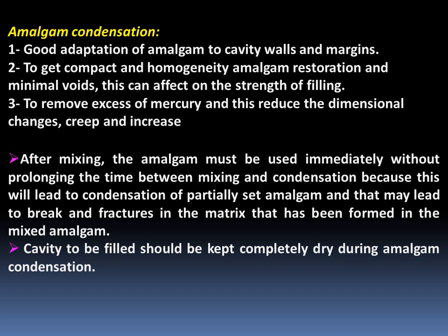So, amalgam condensation is a very important step in order to have a good amalgam and also to get rid of the voids formed during condensation and also to have good mechanical properties and reduce dimensional change of the amalgam. After mixing, the amalgam must be used immediately. Prolonging the time between mixing and condensation will lead to condensation of partially set amalgam and that may lead to breaks and fractures of the matrix that have been formed in the mixed amalgam.